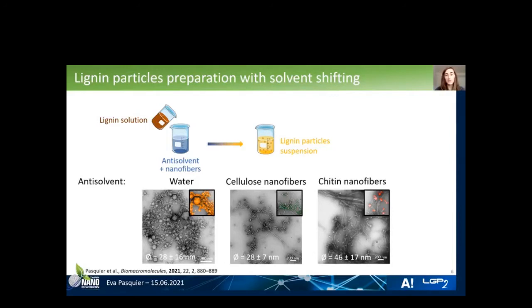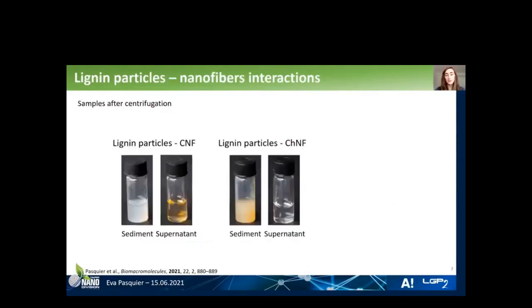where the adhesion is between these. So we looked at the interaction, and for that we did some high-speed centrifugation of the suspension. So the lignin particles with CNF and the lignin particles with chitin fibers. And you can see here, for the CNF, you obtain the CNF in the sediment and the lignin particles in the supernatant because they are stable.